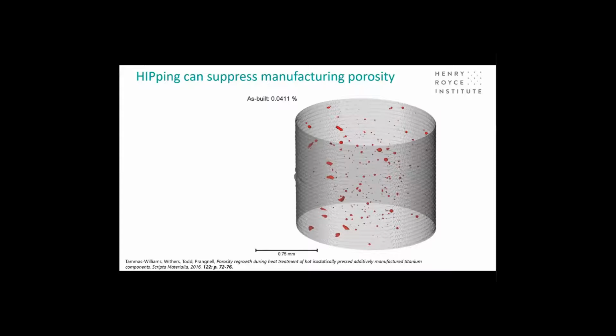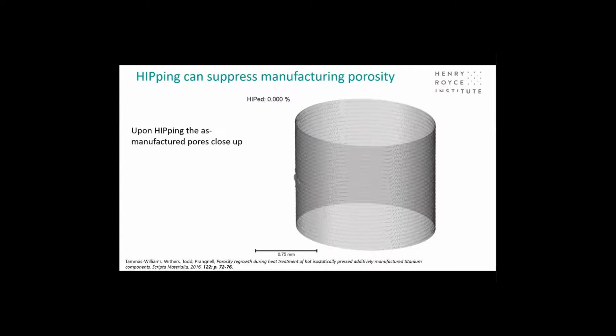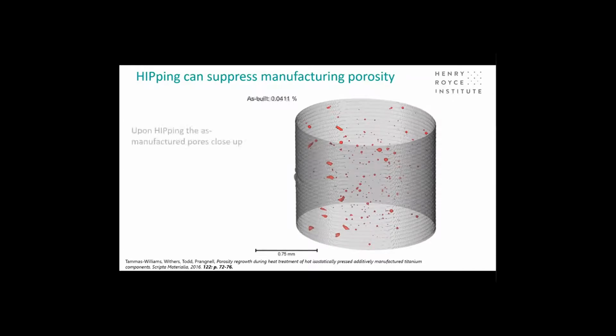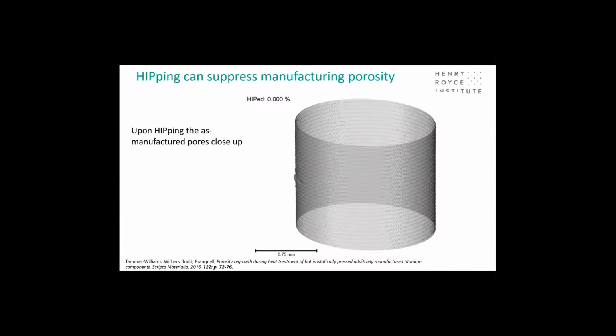Another important aspect is post additive manufactured processing, and you can see here a series of defects in, I think, a titanium sample. So this is a 6-4, and you can see a range of defects, and often post additive manufactured hipping can be used to remove the defects. You can see here that upon hipping, the as manufactured pores have been closed up. But what we can also see in some cases is that when you heat treat the sample, the pores will reopen. So if I just go through those three again, you can see large pores there being largely removed by the hipping process, hot isostatic pressing, closing up those pores. But we can see that after heat treatment, some pores reopen.